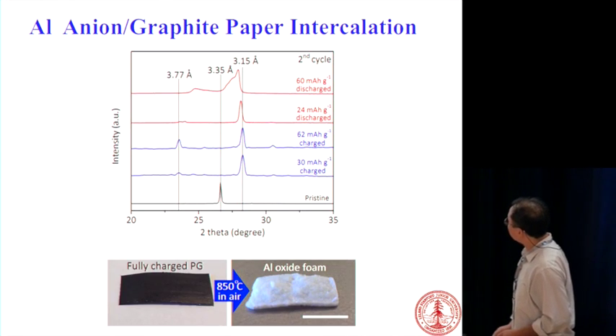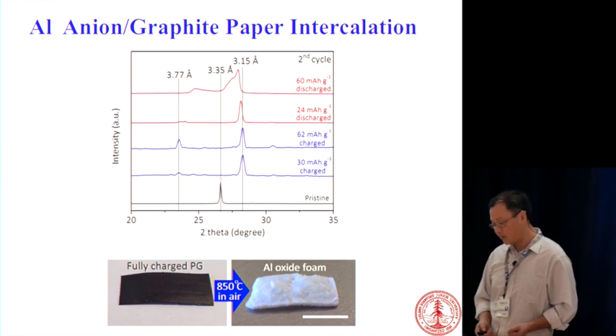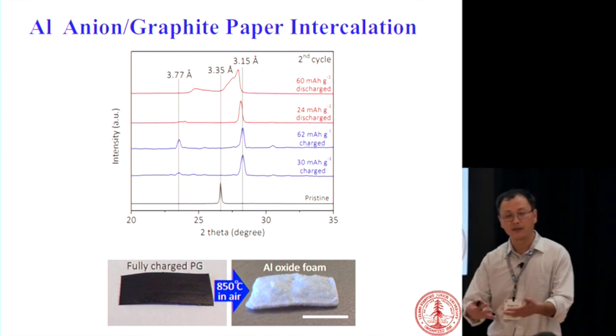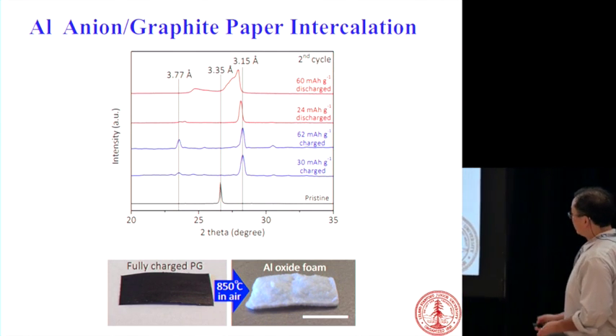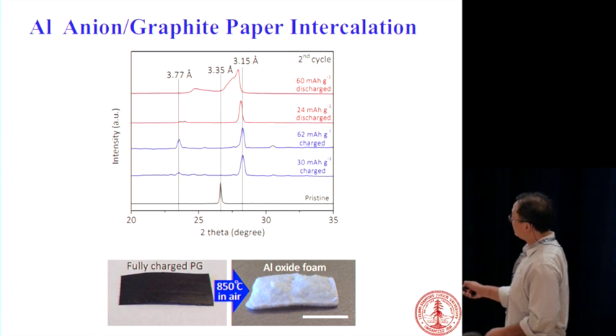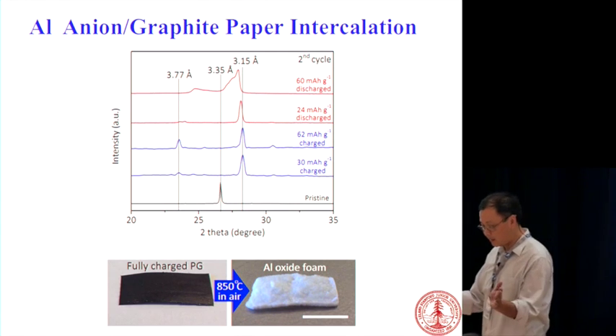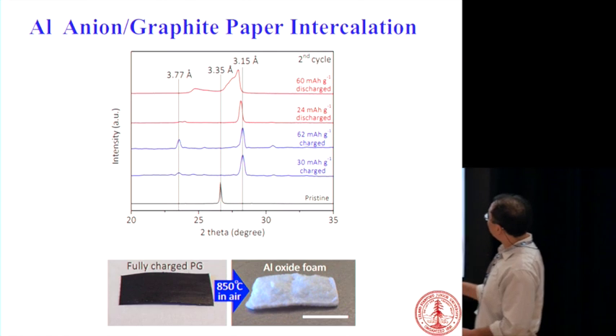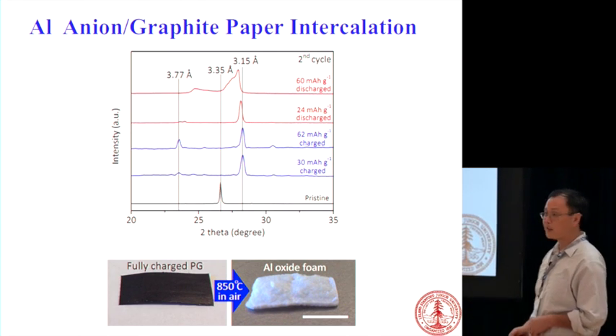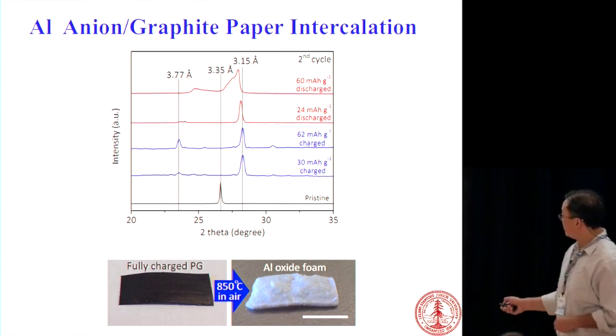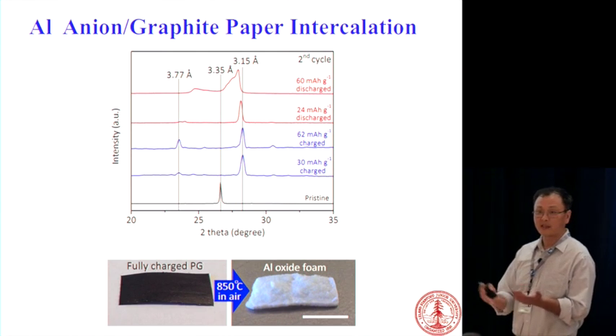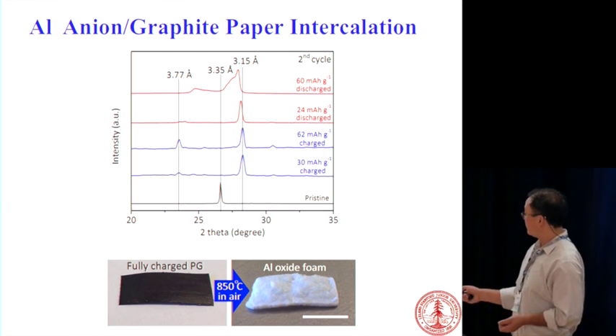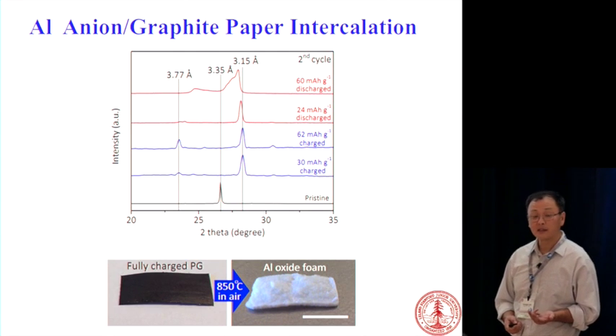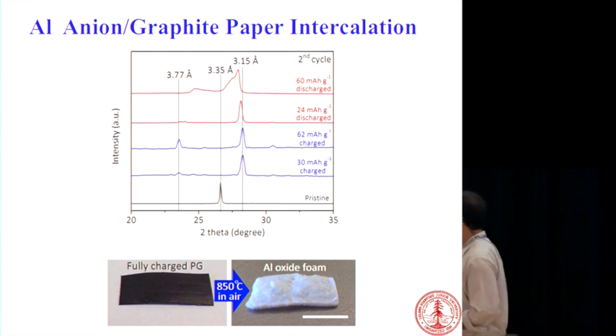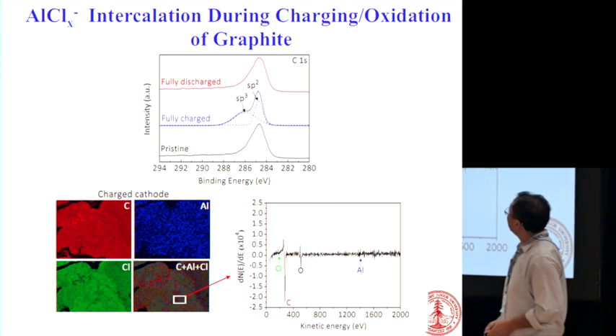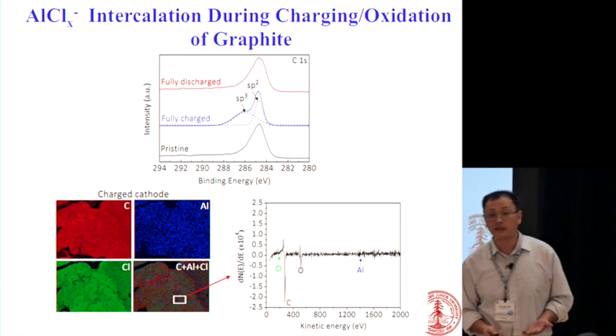Okay, and then we also have done X-ray diffraction studies to look at the anions going into the graphite for intercalation. You can see the D-spacing gets expanded or compressed, and it's more or less reversible from the XRD. If you charge the graphite and burn it up, right, oxidize the carbon, you end up with aluminum oxide. It turns into aluminum oxide foam. You can do XPS to look at the oxidation of the carbon.